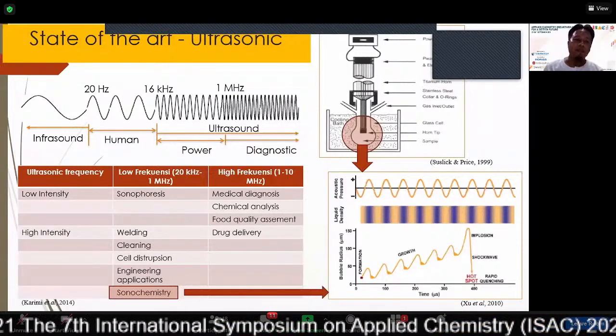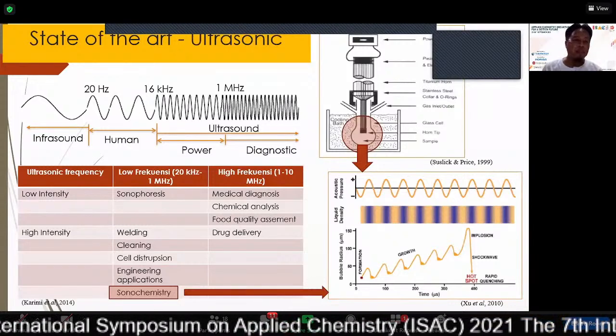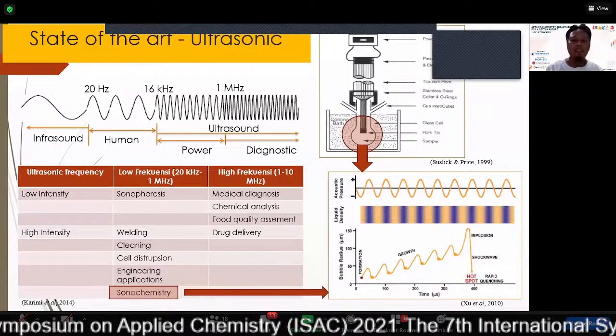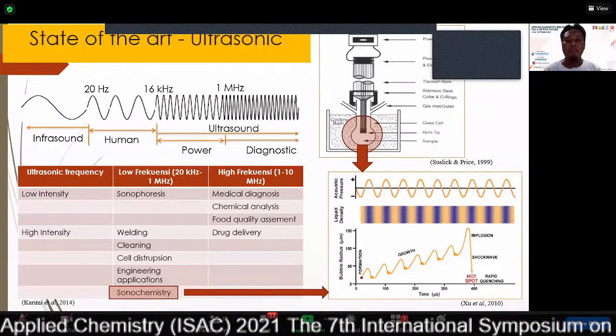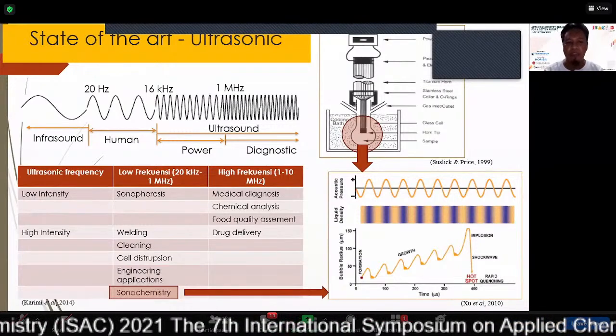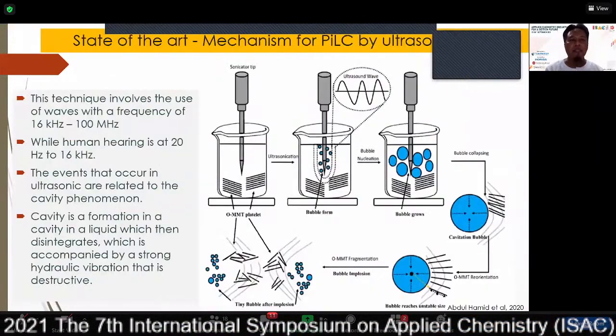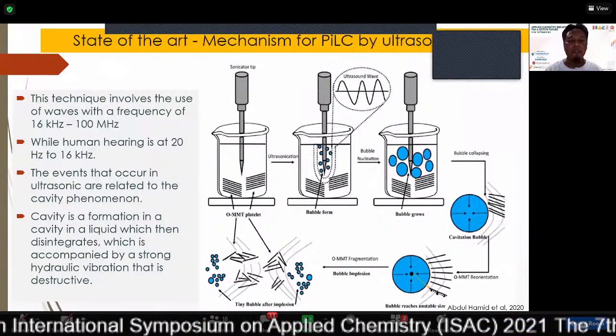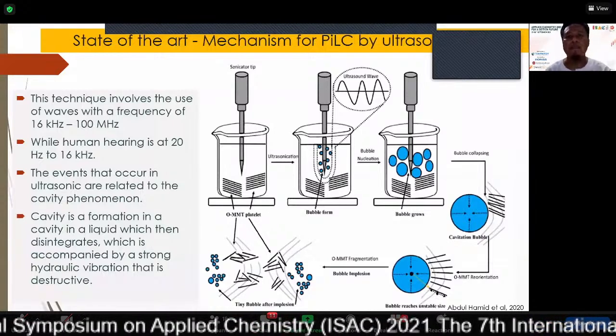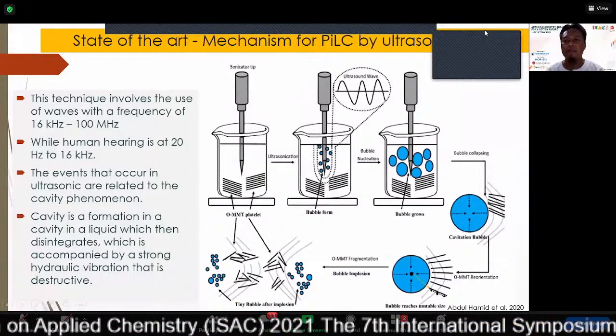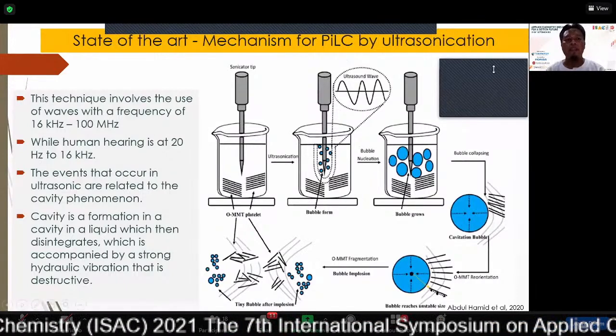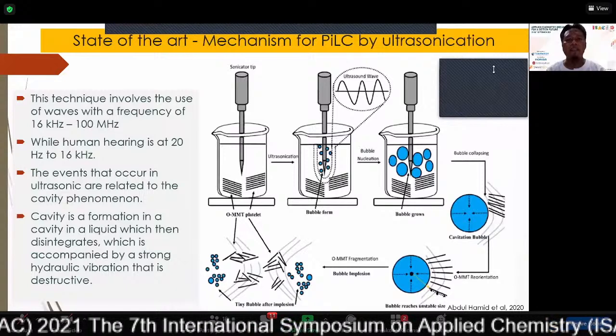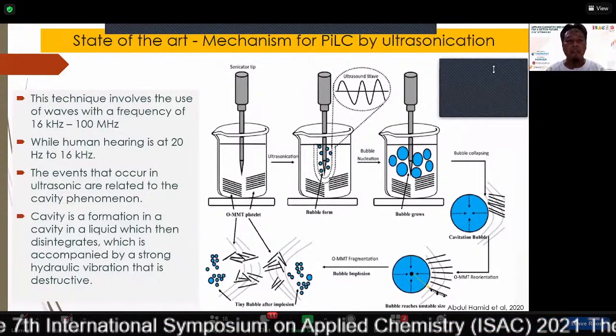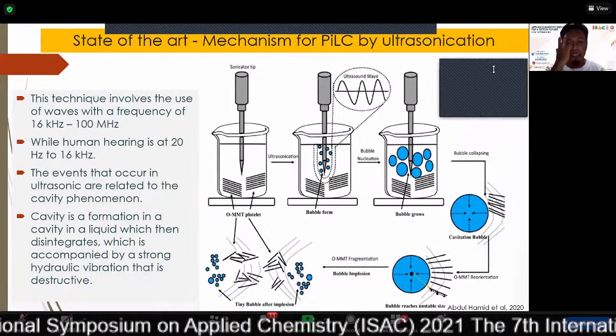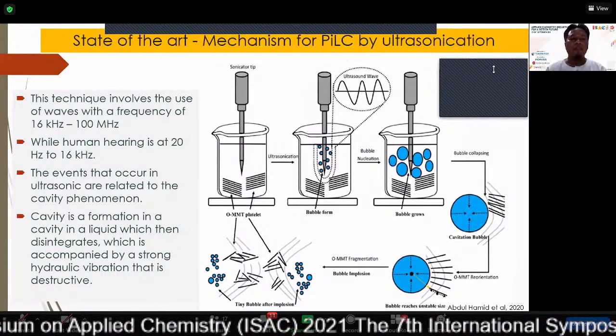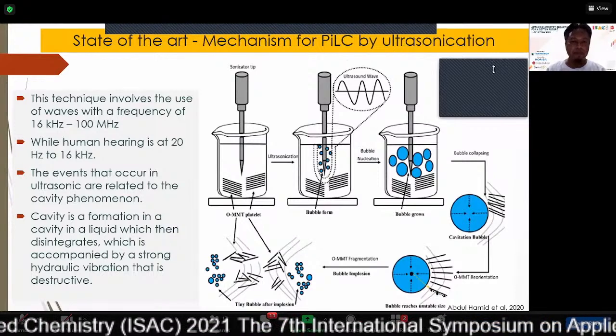State-of-the-art ultrasonic. For sonochemistry, we use a low frequency of 20 kHz and high intensity, more than 50 watts output power. Okay, we will describe the mechanism of PILC by ultrasonic. Ultrasound uses waves with a frequency from 16 kHz until 100 MHz, while human hearing is 20 Hz to 16 kHz.